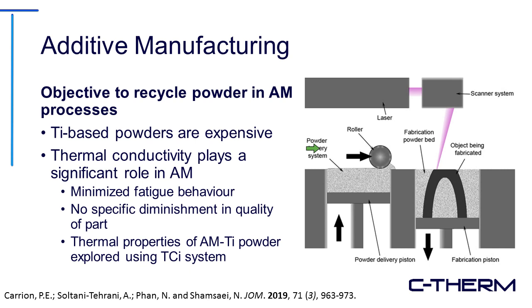So the objective of the research was to look at the effect of recycling these powders. And this is a very important green and a very important economical aspect, as we're looking at these powders, which are based on titanium, around $300 to $600 per kilogram. So being able to investigate and find methodologies which are able to recycle these powders is very important for the industry. Specifically, they wanted to minimize fatigue behavior. They wanted to make sure there's no diminishment on the quality of these parts.